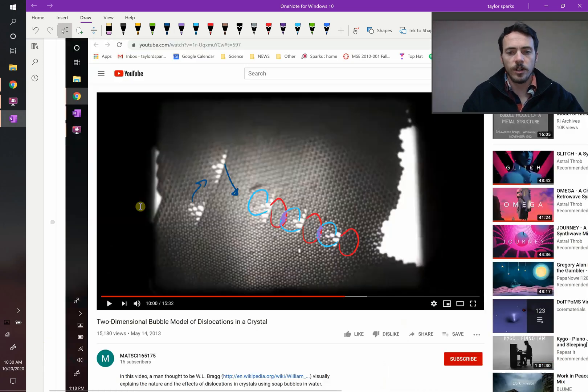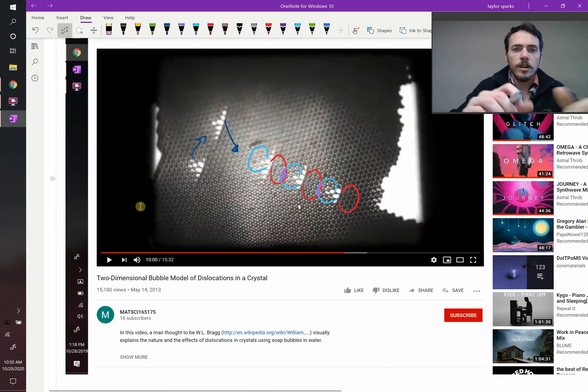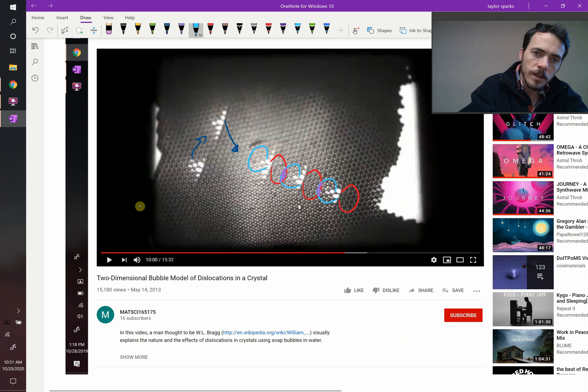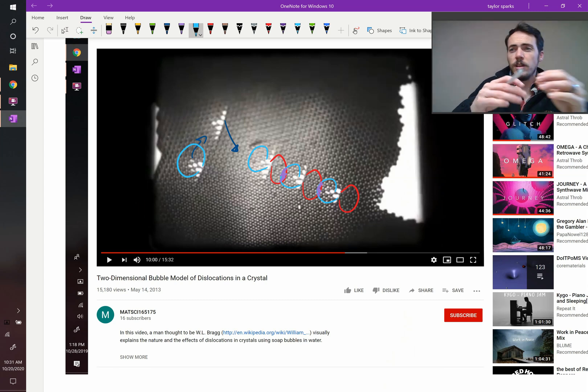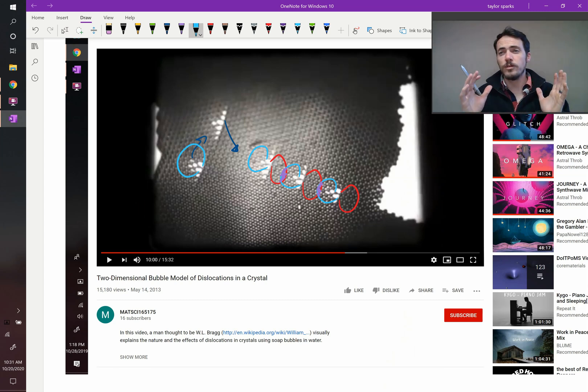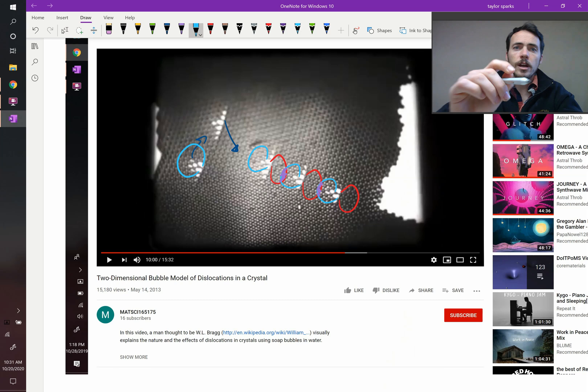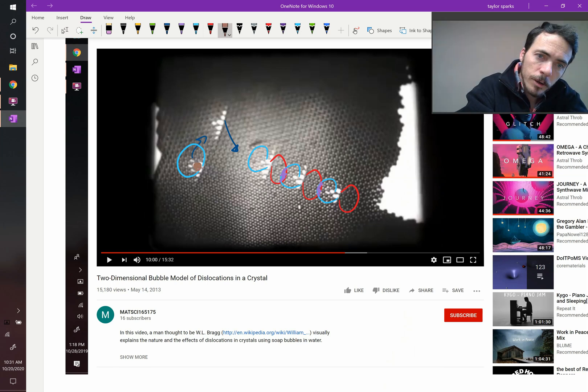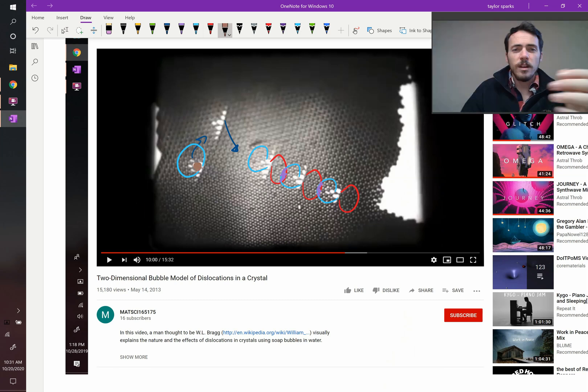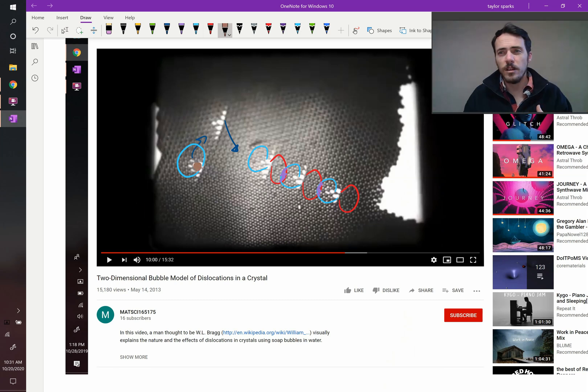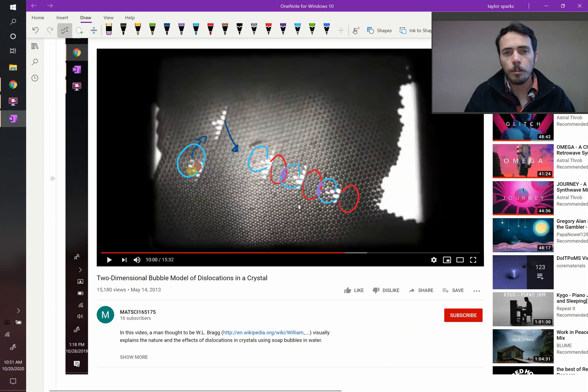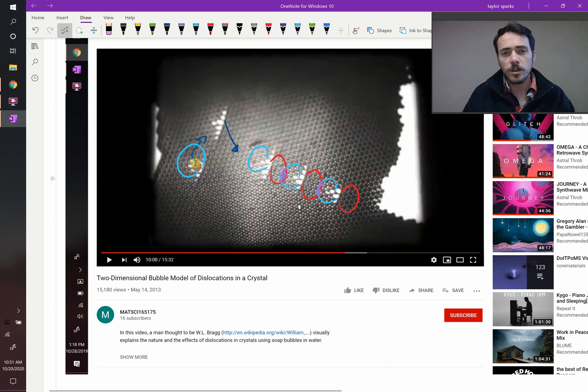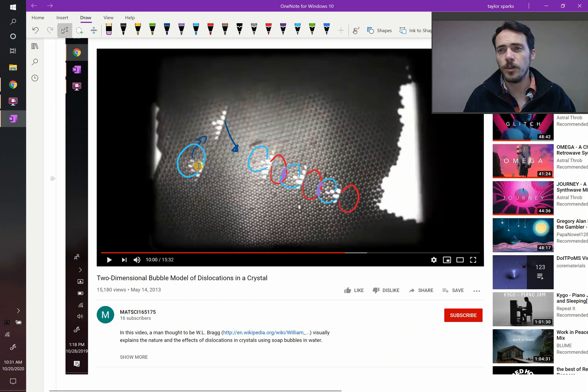Think about what's happening there. If you have an impurity, this region right here is under tension. It's too large. There's too much area and not enough bubble there. So if you've got a really large impurity atom, a big one like that, then it's going to help fill some of that open space that it didn't want to have so open. So once a dislocation finds an impurity, it's going to be more likely to stay put there.